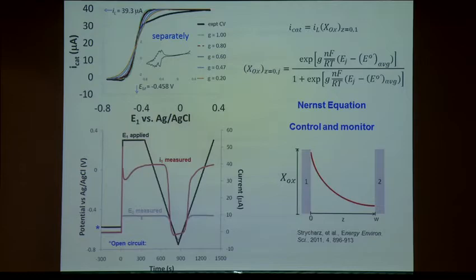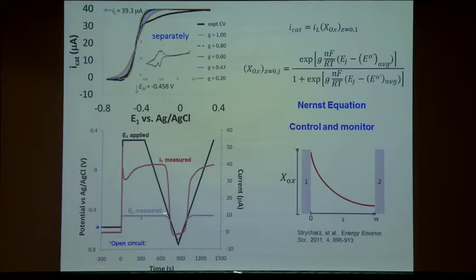Now, I'm sweeping one electrode and monitoring the other. When they're both at open circuit potential, they're both pegged at almost minus 0.6 volts. That's due to the fact that all the cytochromes or charge transfer mediators are being reduced by the persistence of acetate oxidation. After a while, I poise electrode 1 up here at 0.4 volts. Immediately, electrode 2 responds. It's no longer fully reduced. It has gone up a little bit in potential, indicating that some of the cytochromes near electrode 2 are in the oxidized form, so that even though electrode 2 is not collecting electrons, these electrons can be moving from microbes near electrode 2 to the electrode surface.